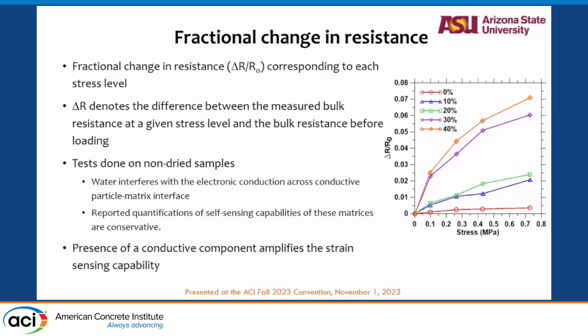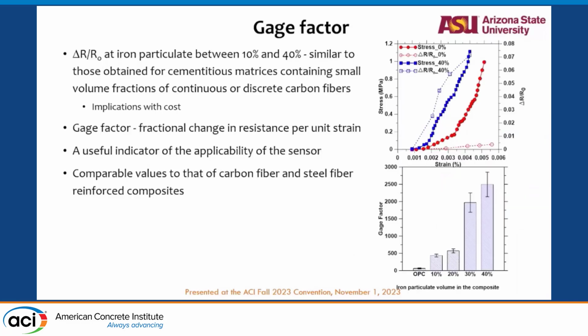The sample that was tested was a wet sample. It was not dried because we wanted water to be there as the conduction medium through the pores too. So basically, based on the stress state and the delta R by R naught, we can,